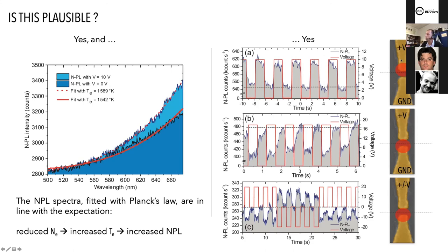When we have a positive bias and we're looking at the positive side, whenever we apply the positive pulse, we have an increase of the NPL signal. And this is consistent with this picture. On the positive side, we have an accumulation of positive charges, holes basically, so a reduced number of electrons, which leads to an increased NPL. Now, if we go to the other side, this is the region where electrons are accumulating. You see the reverse. Whenever you apply the bias, this red curve, you have a quenching of the nonlinear photoluminescence. So it's very consistent with this.